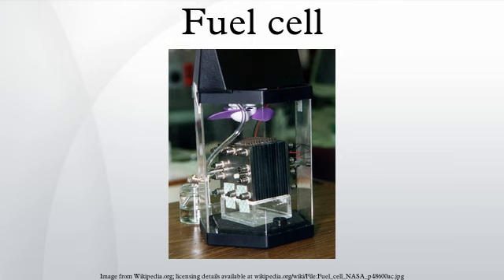Water and air management. In this type of fuel cell, the membrane must be hydrated, requiring water to be evaporated at precisely the same rate that it is produced. If water is evaporated too quickly, the membrane dries, resistance across it increases, and eventually it will crack, creating a gas short circuit, where hydrogen and oxygen combine directly, generating heat that will damage the fuel cell. If the water is evaporated too slowly, the electrodes will flood, preventing the reactants from reaching the catalyst and stopping the reaction. Methods to manage water in cells are being developed, like electroosmotic pumps focusing on flow control.